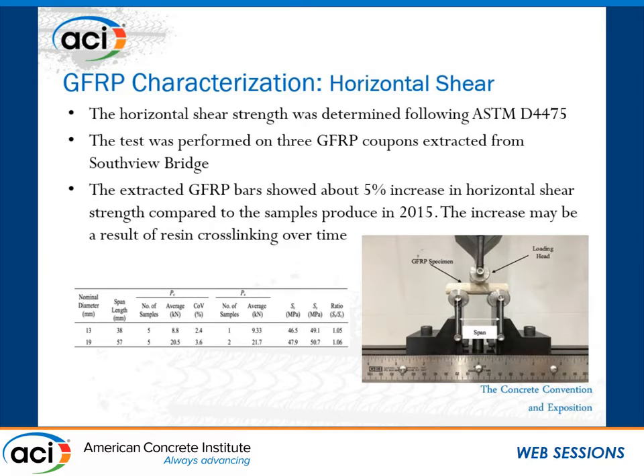So horizontal shear strength was really important for us, but unfortunately for this specific bridge, there was no historical data for the exact GFRP bars used in the construction, so as to be able to compare that. So what we did was we performed the same test with the same setup on the samples produced by the same manufacturer in 2015, and used them as a benchmark of comparison. Because generally we expect the technology to become better and better over the years.